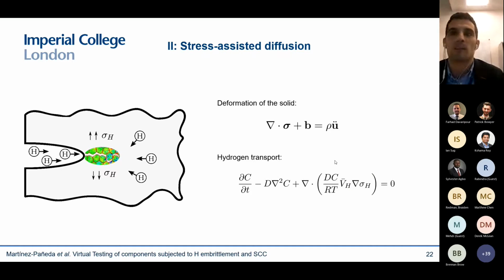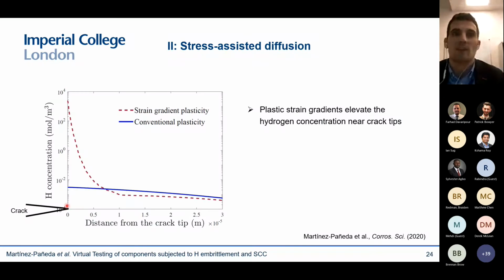In fact, if you get the steady state solution, you'll get something like this. And you see that the hydrogen concentration will depend on an exponential term where all of these are constants. This is temperature, gas constant, partial molar volume, and this is the hydrostatic stress. So it is very important to get this term right. And in fact, when we couple this deformation diffusion model and we predict the hydrogen concentration ahead of a crack, you can see that with conventional continuum models, we're okay until we get to this distance ahead of a crack tip where we see a much higher hydrogen concentration.